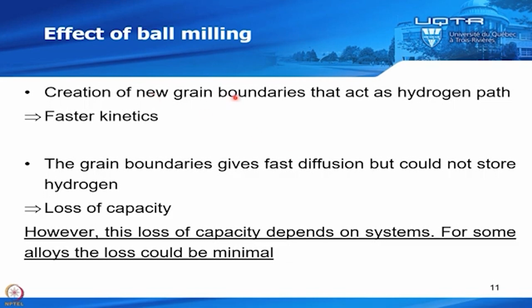So then we could explain the loss of capacity. So when you create a new grain boundary, this acts as a hydrogen path, as we saw in the first part. So this means that it's fast kinetics because now you have more grain boundary, so you have more paths for hydrogen to go into your crystallite. But the grain boundary gives a fast diffusion, but it cannot store hydrogen. So hydrogen is going through the grain boundary, but doesn't stay there. So you have a loss of capacity. And of course, the more grain boundary you have, the less capacity you will have. And you see that for iron titanium, this scales perfectly well.